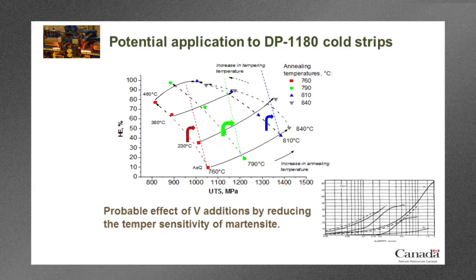Now, this is very interesting. Let's just concentrate on the red points for the moment. This is the steel with 38% ferrite. We've annealed it at 760 degrees C, and we have a very low hole expansion coefficient. It's only about 10%. And if we temper it, then we'll follow this dotted curve here.